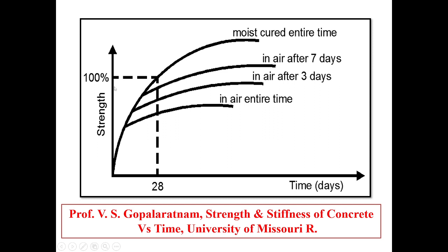Approximately it becomes 80%. Again, one graph below it, the third graph, is concrete in air after 3 days. That means the concrete was cured only for 3 days and then left in the air, and when it was tested at 28 days, the strength still dropped, maybe to around 60%. And when the concrete was in the air the entire time, that is the last graph, that means no curing was applied, we can see that at 28 days the strength is only about 50%. So that is the importance of the curing period. That means the more time you cure, the more strength it will gain.